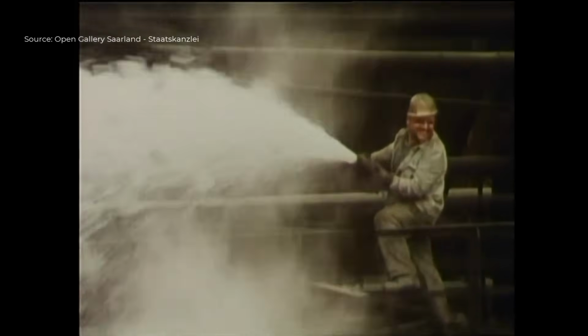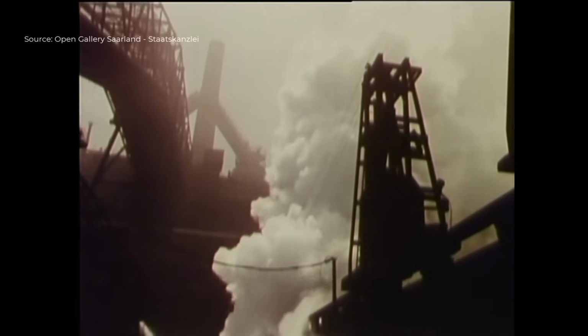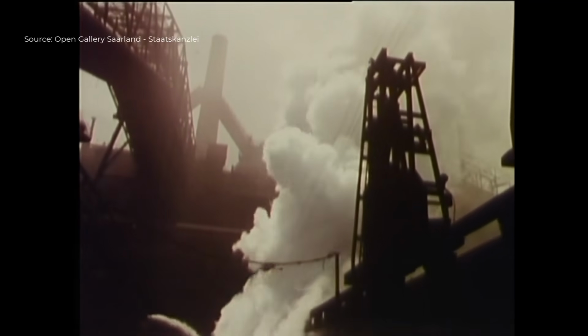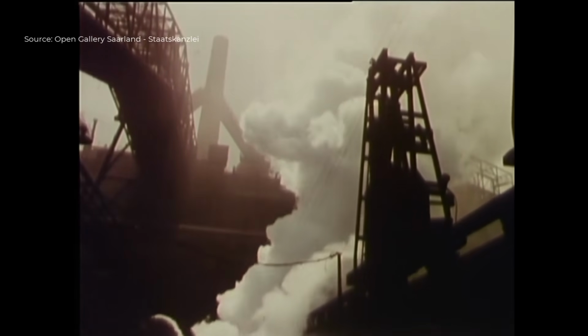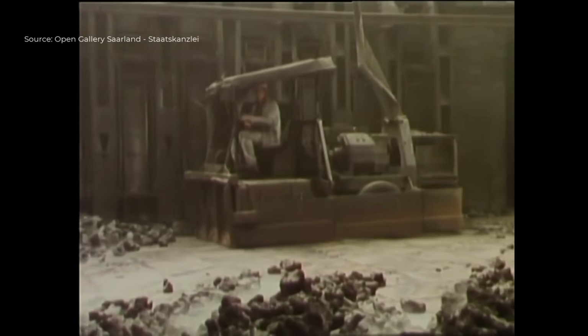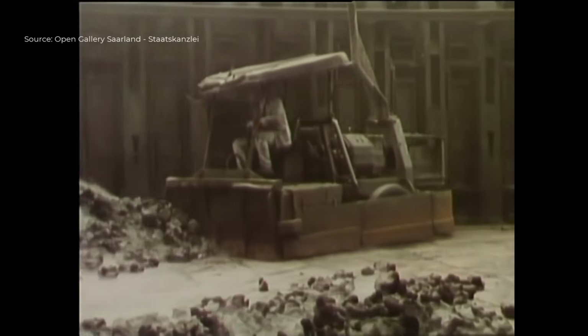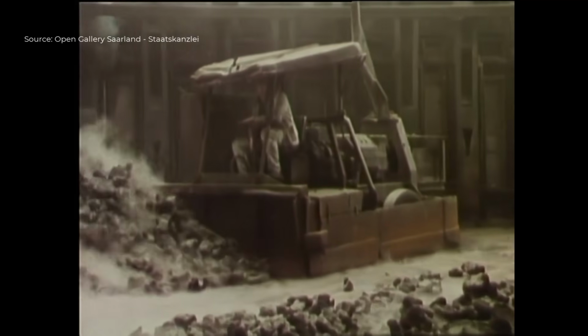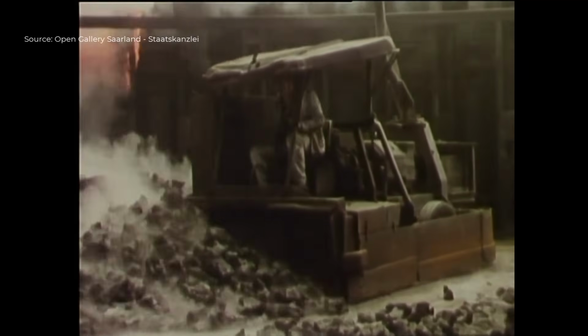After many hours of heating, the glowing coke was pushed out of the ovens by a mechanical pusher machine. The incandescent material fell into a quenching car, which transported it to the quenching tower. There, the coke was rapidly cooled with water, producing dramatic clouds of steam that rose high above the facility. This step ensured the coke achieved the necessary mechanical strength for use in blast furnaces.